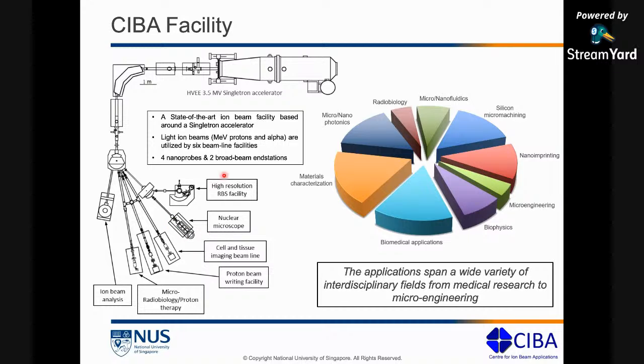And then we have this last beam line here, which is the high resolution RBS facility. This one is kind of a special system where, for example, if you have a thin film on the order of 10 nanometers or 5 nanometers or even lower, and you want to measure its thickness and measure its composition, this system works best for these kinds of samples. And so this has a very good energy resolution and a very good depth resolution.